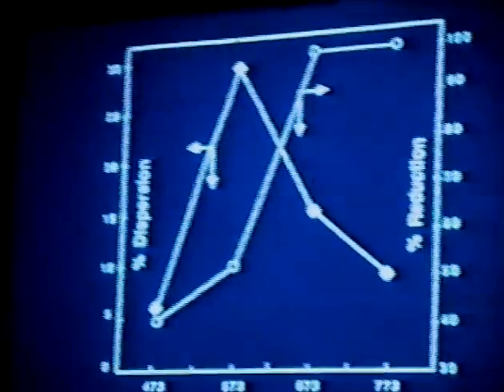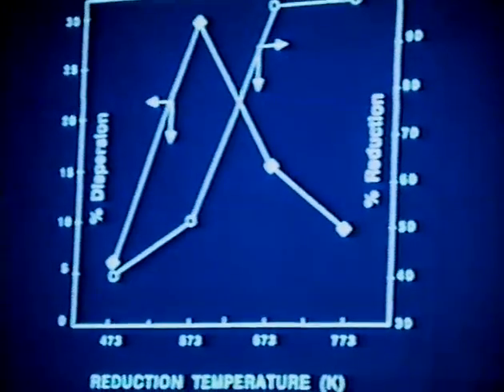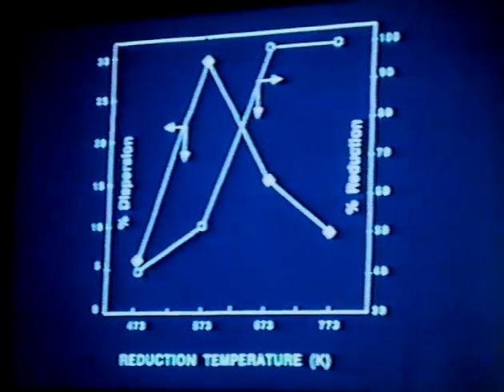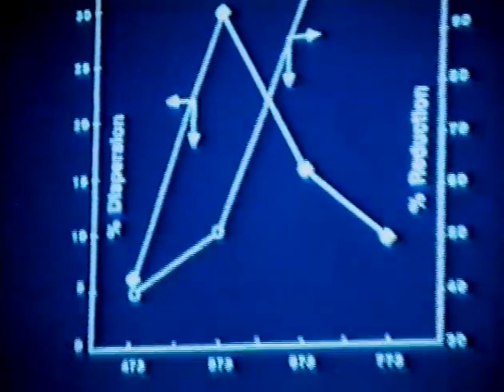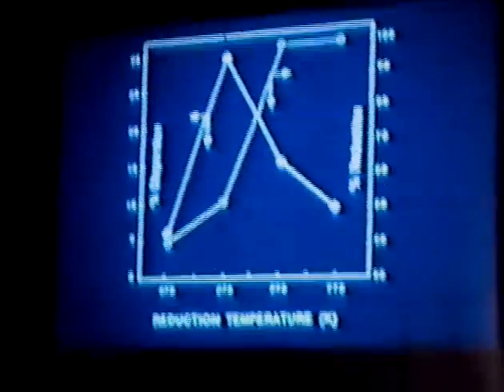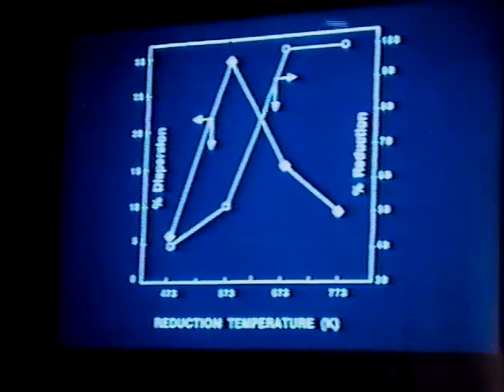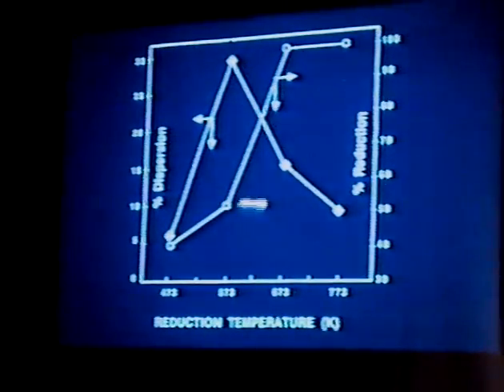In order to get a good reduction temperature for this purpose, we reduced the iron pentacarbonyl impregnated catalyst, and this is for a 4.5% iron alumina catalyst prepared on a support that was dehydroxylated at 650 degrees centigrade. We find as the reduction temperature increases, the dispersion goes through a maximum of close to about 30% for this catalyst, and the extent of reduction essentially goes to 100%. Higher reduction temperature rendered this catalyst poorly dispersed. Therefore, in all our studies, especially the iron catalyst, we used 300 degrees centigrade as our reduction temperature.